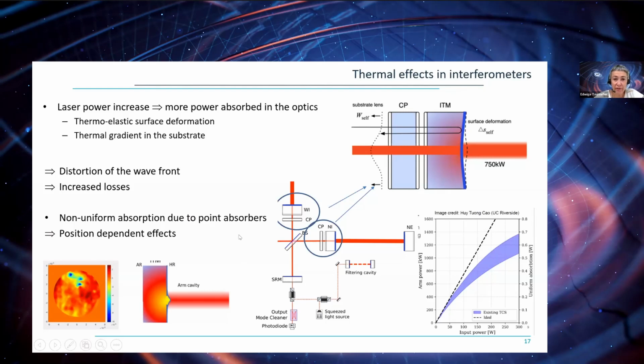There is an additional effect, which is non-uniform absorption, which is due to point absorbers that we found during the O3 run, due to some small particles which are embedded in the coating of the mirrors, and which induce some local deformation, which is even more annoying because it's much more complicated to correct.